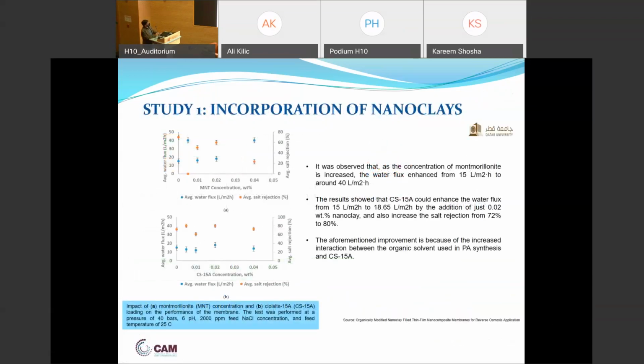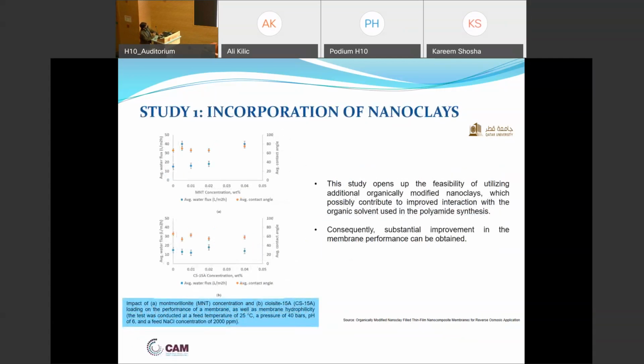So these are some of the performance results you can see here. On the left side is average water flux, and on the right side is the salt rejection. As we increase concentration from 0.01% to 0.05%, even with very small incorporation, they have shown very promising results with two different nanoclays. At the same time, they have shown very high hydrophilicity, which is indicated by the contact angle.